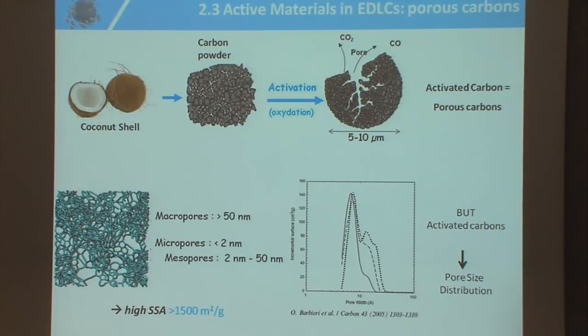However, it's very difficult to control this process, activation. It's very difficult to control the pore size of the carbon you are producing. So this is a porous volume versus a pore width, pore size, in Angstrom. So you can see this is a very narrow pore size carbon, and you can see that the pore size goes between, I would say, 0.5 to 4 nanometer, which is very large, in fact. And for 10 years, there was no way to find a way to prepare carbons with very narrow pore size distribution.